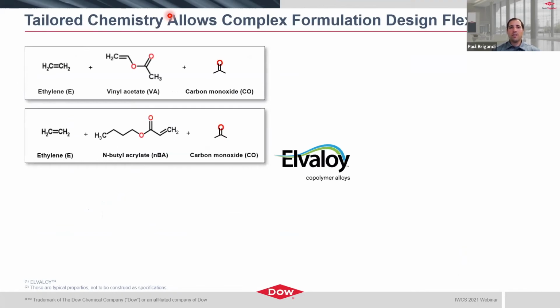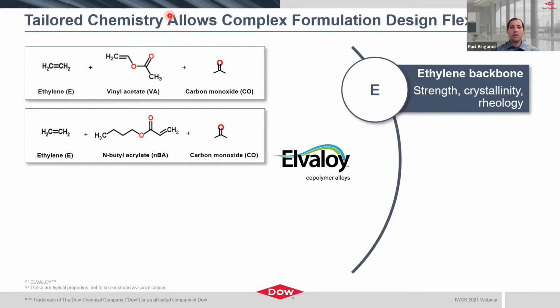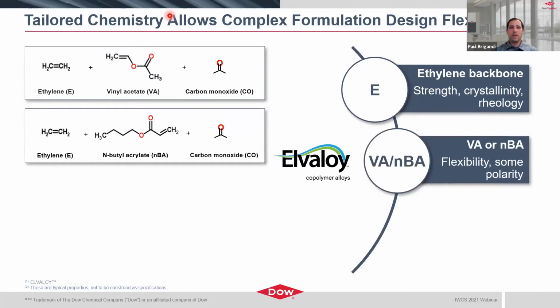So what we'll talk about today, and you'll see throughout the course of the presentation, are two main types of ethylene copolymer modifiers. And these are both containing an ethylene backbone, and that ethylene backbone is really there to impart strength, crystallinity, and mainly controls the processability of the material. We add in a second co-monomer, whether that be vinyl acetate or butyl acrylate, difference being in the length of the side chain. That's really going to impart some flexibility to the polymeric modifier, as well as start to introduce some polarity, which is important for miscibility with PVC.